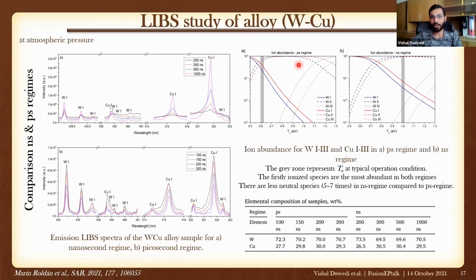Also, we calculated the ion abundance in the picosecond and nanosecond regimes. The gray zone represents the temperature at typical operation conditions. For nanosecond, the typical condition is around 1 electron volt; for picosecond, around 0.6 electron volt. The firstly ionized species are the most abundant in both regimes, the dotted one here. And there are 5 to 7 times fewer neutral species in the nanosecond regime in comparison to the picosecond regime.